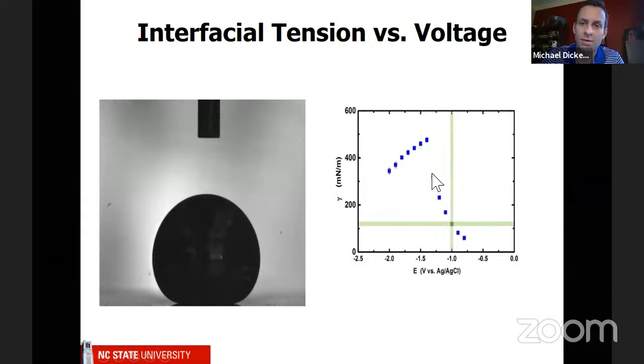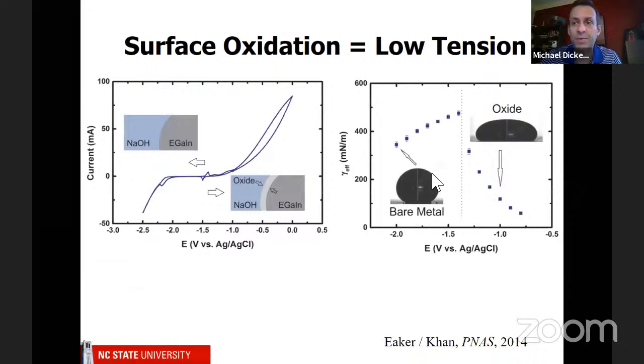So we had to make some electrochemistry measurements. And I'm not going to go into a lot of detail, but basically we measure current while we apply the voltage. And you see right here, this is 0. So we start, remember, around negative 1.5, and we start applying a potential, and we see a little bump. And where you see that bump, that means there's a reaction occurring. There's electrochemistry happening. And so if you draw a dotted line down around this bump, around here, now I'm going to go over to this chart, and I'm going to put that same dotted line, and that's exactly where we see this weird behavior.